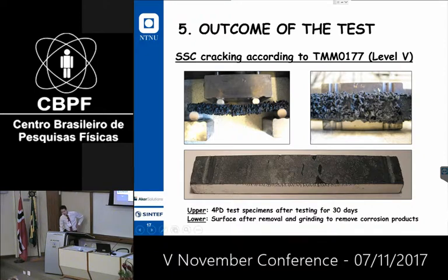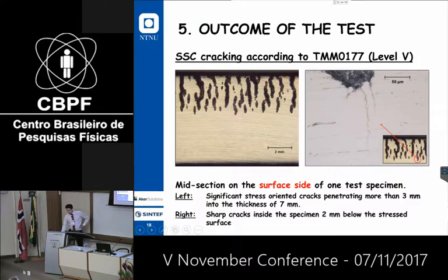So you can see here, we still have no broken samples. However, almost half of it was cracked and there were corrosion deposits on the surface. You actually see the corrosion here when you scrape off that deposit layer. So 3 millimeters into the sample, we had this cracking, and this is a blow-up of the cracks, penetrating perpendicular to the applied stress, but also lower down in the material, sharp cracks below, not necessarily oriented in an orderly manner.